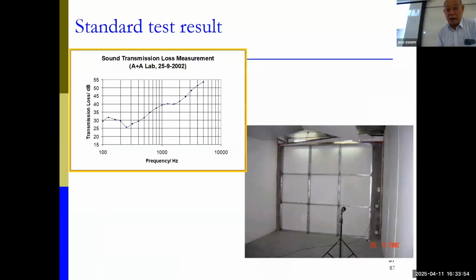And later we generated the second generation, which we used for the 3x3 wall test, and the test results also showed very good. You can see at this low frequency, we have about 30 dB.